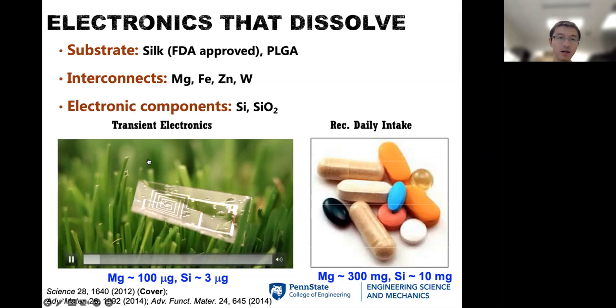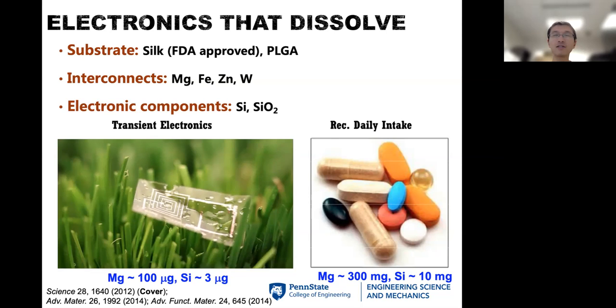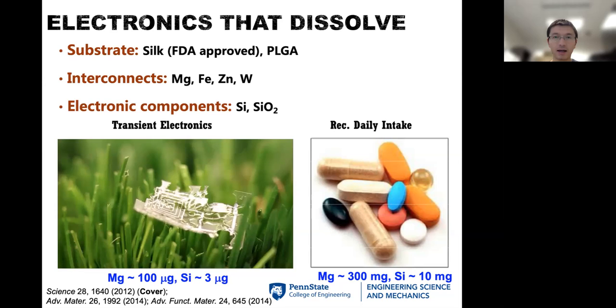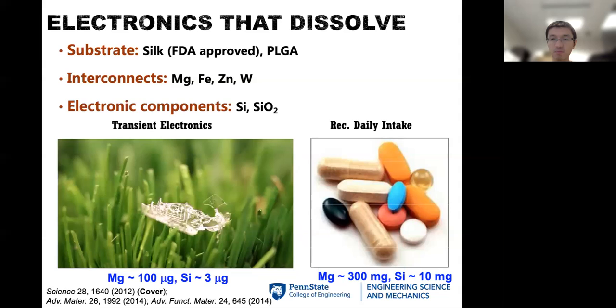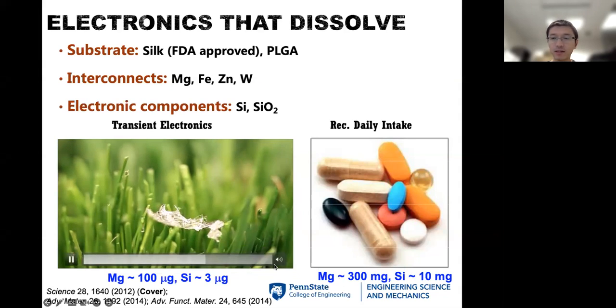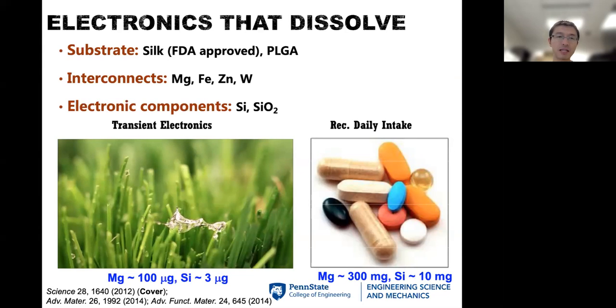So for example here, if we design electronics to be small in thickness, it can safely dissolve after a few days or weeks, depending on the design. And more importantly, the silicon and the corresponding materials we use in electronic components are much smaller than the daily intake. The silicon in our daily intake is about 10 milligrams, and the silicon we use in our device is about 3 micrograms. So 1,000 times smaller silicon will create minimum adverse effect on the human body.